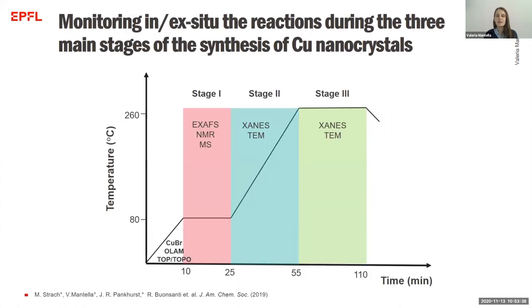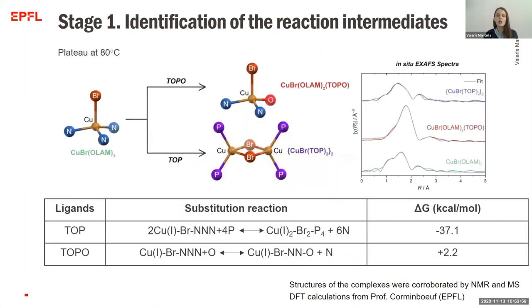So the synthesis that we are studying consists of three main stages. First, we have a plateau at 80 degrees, then a heating ramp to 260 degrees, and then a plateau at this final temperature. And we monitor each of these stages by complementing in situ X-ray absorption spectroscopy with ex situ TEM, NMR, and mass spec. So using our in situ reaction cell, we collected the XAS spectra for the reaction mixture